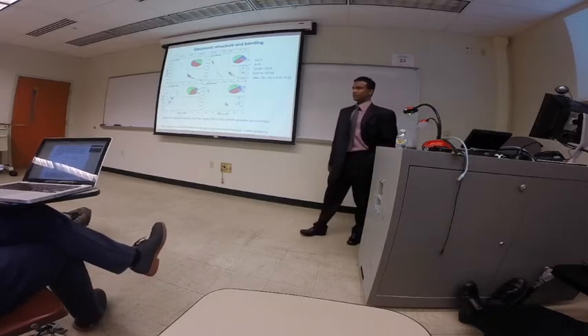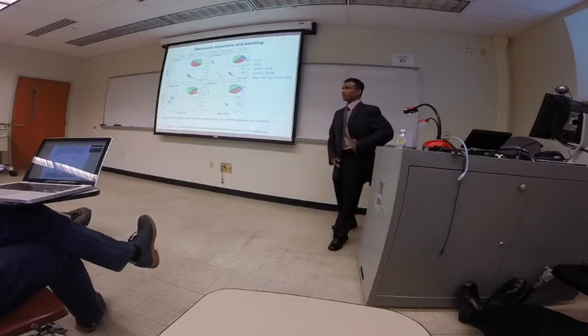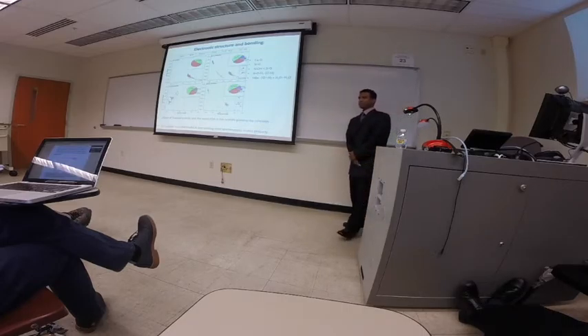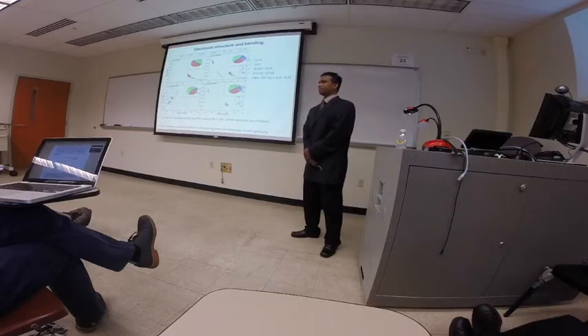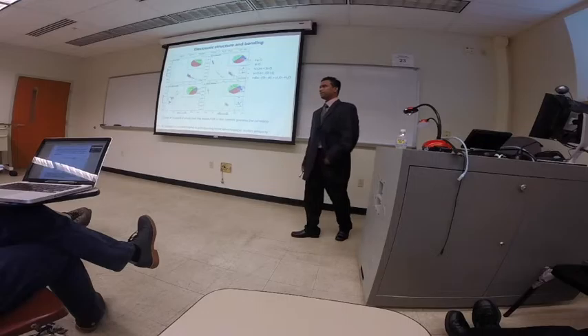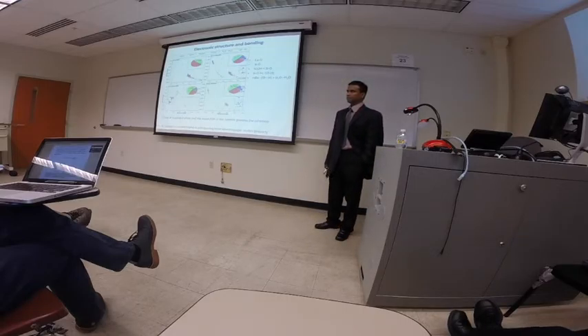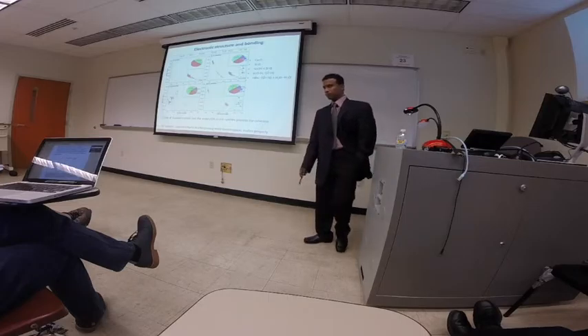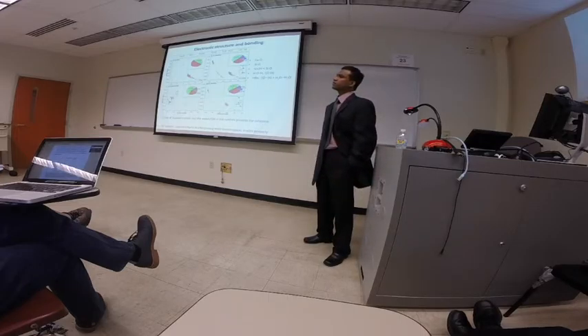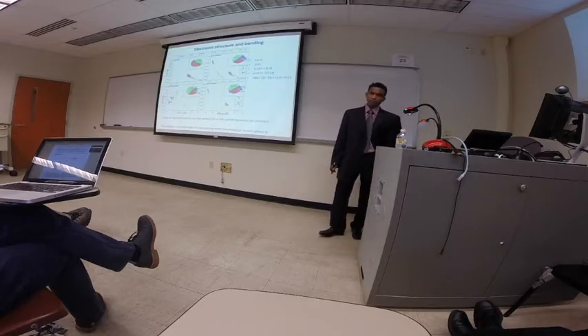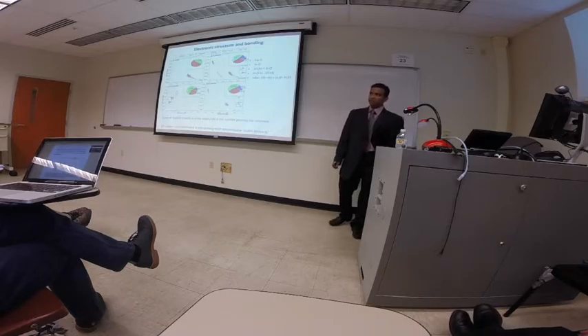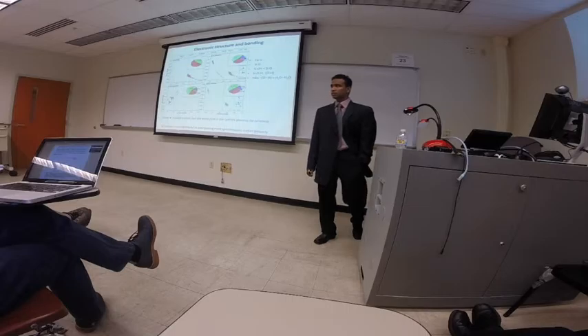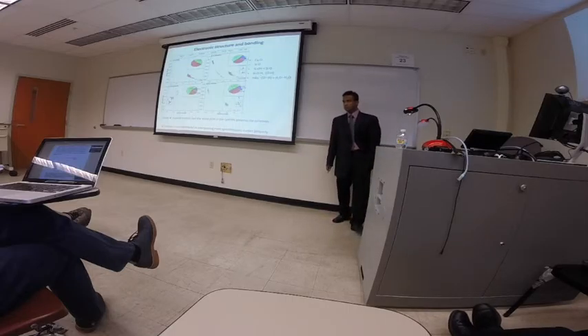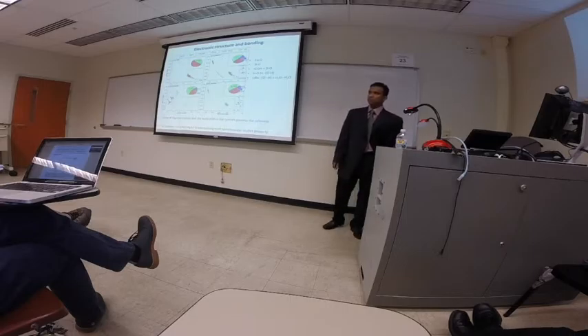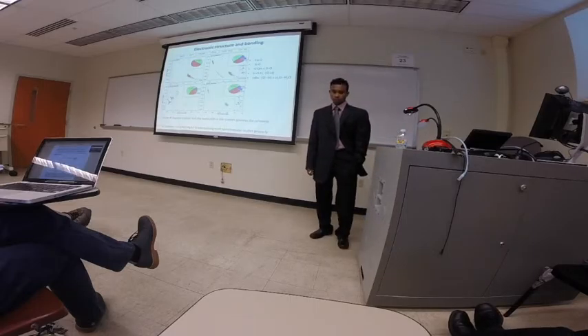I have one last comment, and it's only a comment, not a question. You obtain the elastic constants and mechanical properties in two ways, from ab initio MD and also from stress and strain. But the constants obtained from the stress-strain relation are all within the linear elastic regime, which has its own limitations. The future is in very accurate, large-scale simulations, which would include nonlinear effects. So this is only a comment.